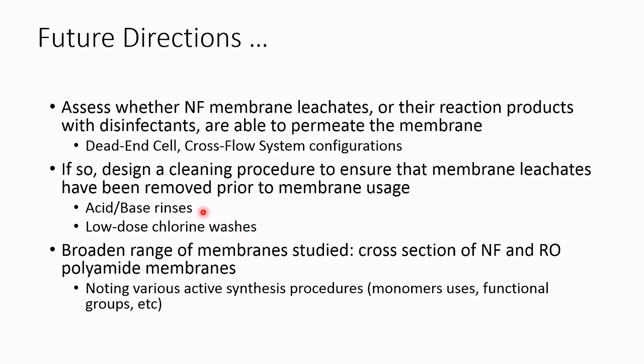If so, and they are, the next step would be to design a procedure that would ensure that these membrane leachates have been removed prior to membrane usage. So typically what's used are acid-base rinses or very low dose chlorine washes. And just making sure that those are suitable for removing some of these leachates coming off of the membrane. And of course, another target would be to broaden the range of membranes studied. So right now we only looked at a nanofiltration membrane, and we only looked at one type of nanofiltration membrane, and that was NF90. So it would be interesting to see what kind of byproducts can be detected from various nanofiltration, reverse osmosis, semi-aromatic, fully aromatic type of membranes.